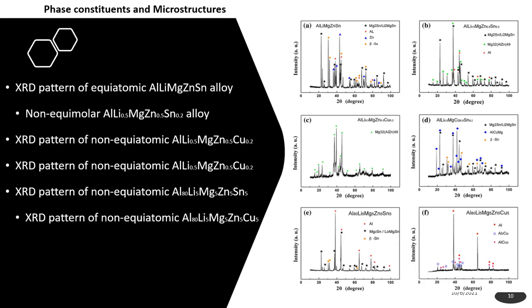Equiatomic alloy, I mean all of the parent elements have the same equiatomic proportions. Okay, so the diffraction pattern of this equiatomic alloy, which is the first one, reveals a distinct reflection of magnesium tin as well as lithium magnesium tin phases. In addition to this, the aluminum, zinc, and beta tin phases were also identified. And you can see the peak intensity as well as the position as identified in the view graph.